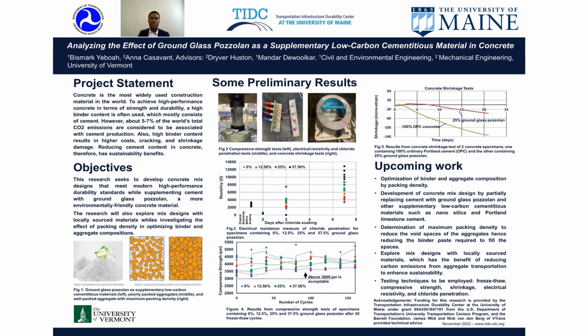To achieve high-performance concrete in terms of strength and durability, high binder or cement content is often used. However, about 5% to 7% of the world's CO2 emissions are associated with cement production and transportation. Also, higher binder content results in higher cost, concrete cracking, and shrinkage damages. Supplementing binder content with supplementary low-carbon cementitious material will result in the reduction of CO2 emissions, relatively lower cost, reduction in concrete cracking and shrinkages, thereby contributing to the sustainability of our environment.